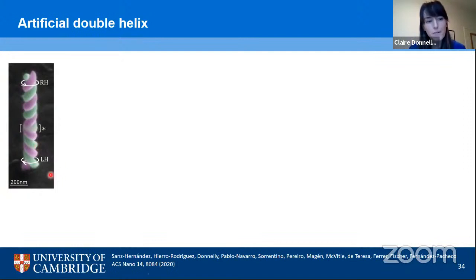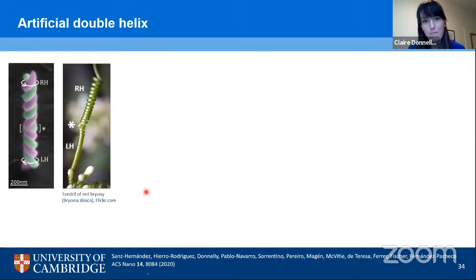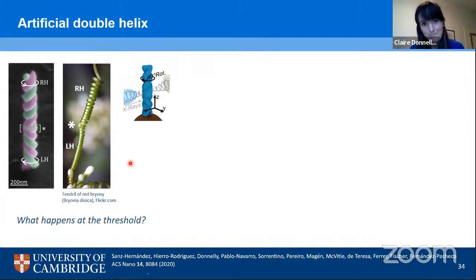This meeting or threshold of the chiral regions is slightly reminiscent of what we quite often see in nature, which is known as a tendril perversion, where regions of different chirality can meet at a certain point. And it may also remind you of old telephone wires, which often had these defects. Now, the question that we want to ask is, what happens at this threshold from a magnetic point of view? In order to understand more about what's going on, as we've done in the past, we measure XMCD images from many different orientations in order to use this angular information to understand what's going on.